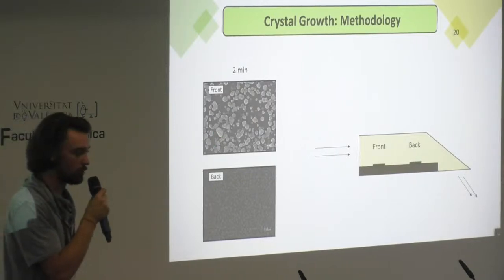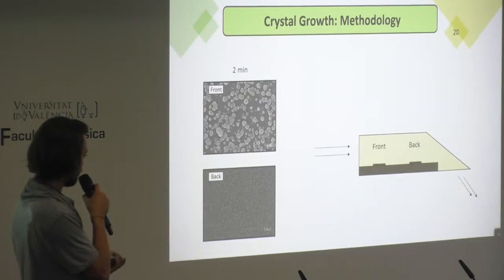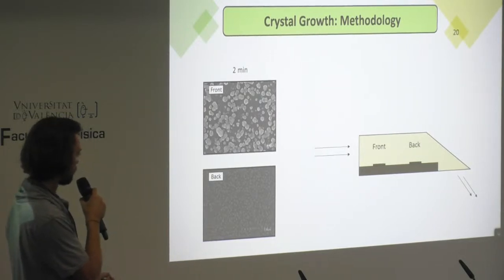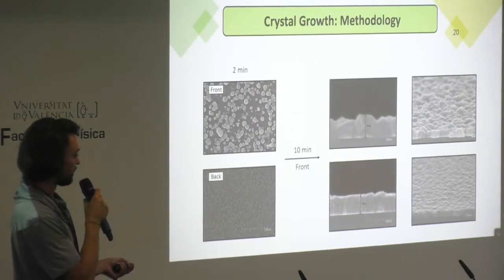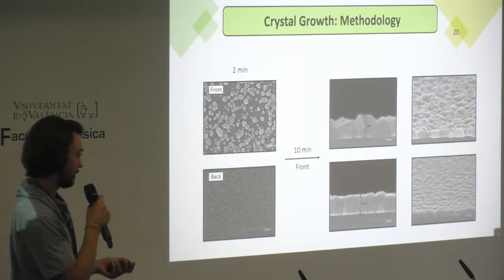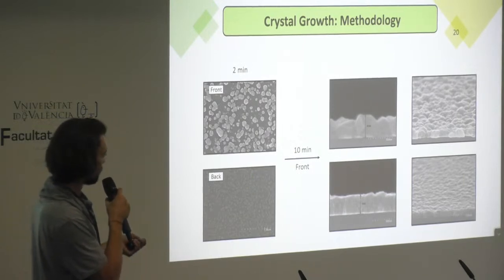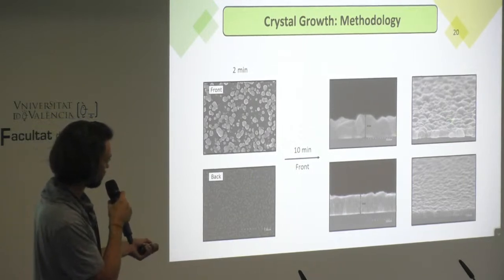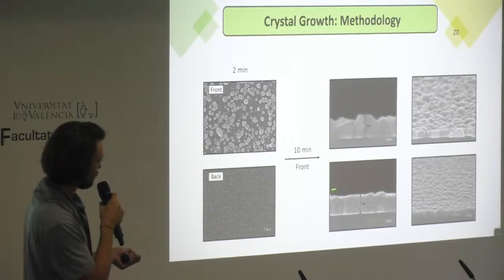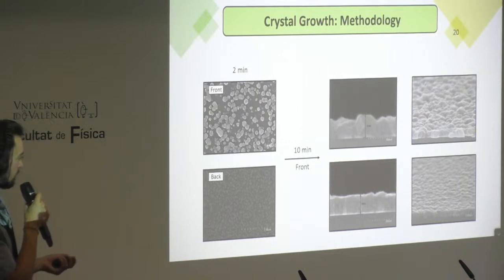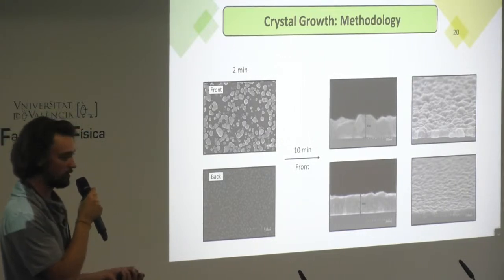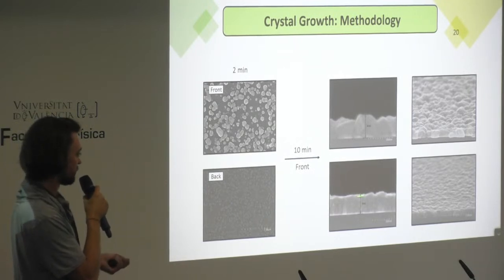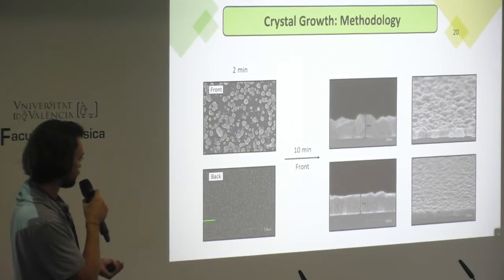Afterwards, we decided we wanted to do thin films, and this sample was very, very useful, because if we have more particles, when they grow, they will find each other earlier. So we go from having nasty films like this, which are like a lot of mountains, to having something that is very thin. So this is an example of how studying your system, even if it doesn't look like it will have applications, is very important, because later on you can use these results you've obtained before.